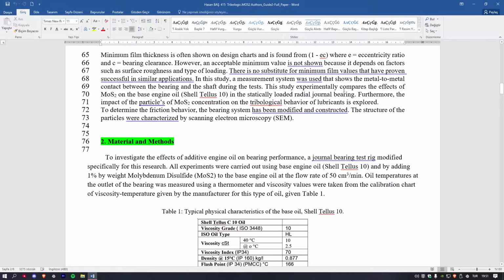In these experimentally working sections, this study experimentally compares the effect of molybdenum disulfide on the base engine oil Shell Tellus 10 in the statically loaded radial journal bearing. Furthermore, the impact of the particles of molybdenum disulfide concentration on the tribological behavior of lubricants is explored. To determine the friction behavior, the bearing system has been modified and constructed. The structure of the particles was characterized by scanning electron microscopy.